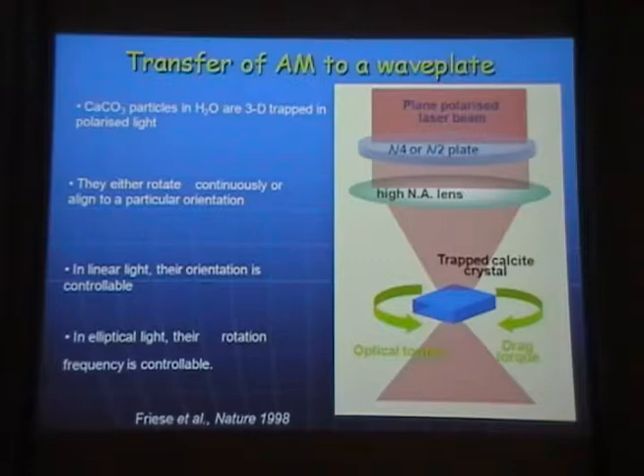And then if the material is highly birefringent, of special thickness, which is lambda over 4, then if you put linearly polarized light on it with optics axis 45 degrees to it, then you will get on the output of that plate circularly polarized light.